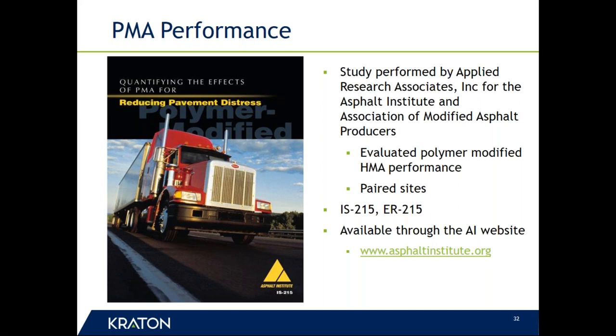At any rate, what they were doing, they were taking a similar approach to what they were doing in development of the AASHTO Mechanistic Empirical Design Guide, which was take test sections, and then they would look at the performance of those test sections, develop transfer functions between response models or response under load to distress types and pavements. They were able to identify a number of paired sites to where the only variable was polymer modified versus unmodified asphalt binders around the United States. And so they went out and evaluated those sites, used that same process to develop transfer functions for unmodified materials and for modified, so that there could be a side-by-side comparison on that. That information is summarized and detailed in the two publications that you see there that are both available through the Asphalt Institute website.